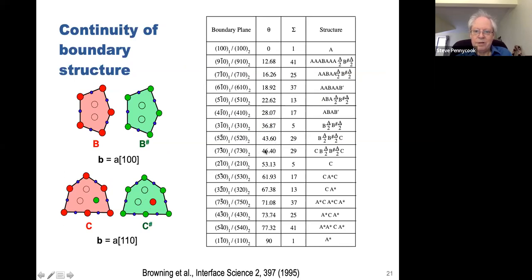All except around 45 degrees, actually, where you could predict the structure of a straight grain boundary, but nature had different ideas and faceted these boundaries into asymmetric 100 and 110 segments. So we did look at asymmetric boundaries as well, and they also follow a structural unit model.